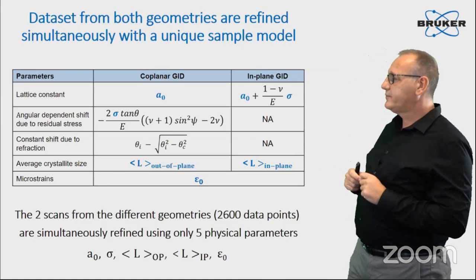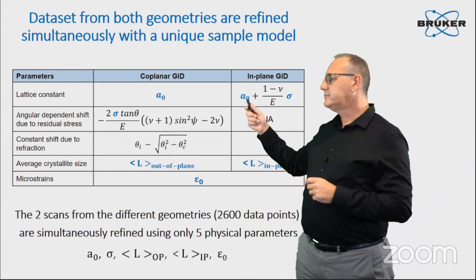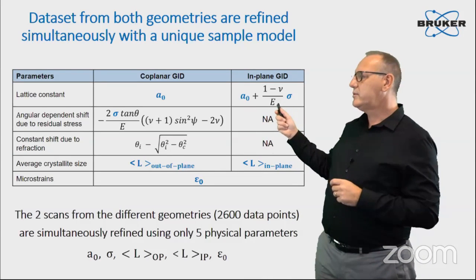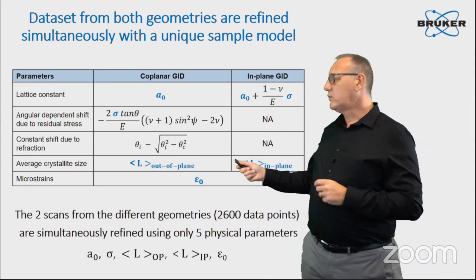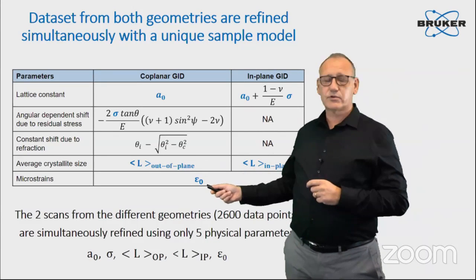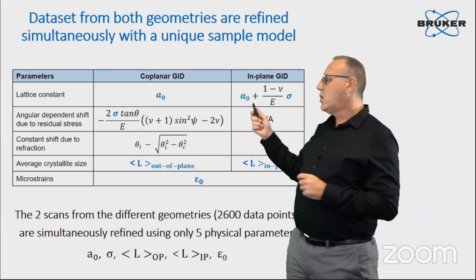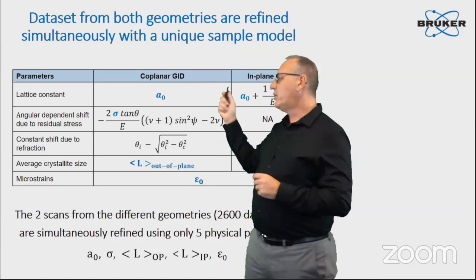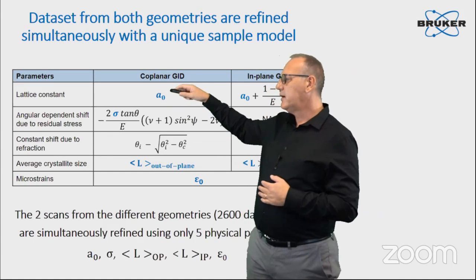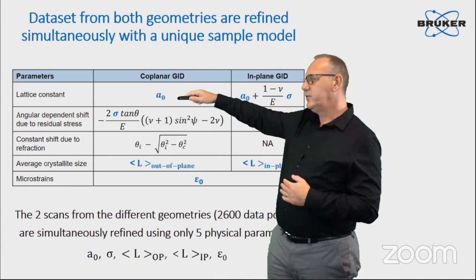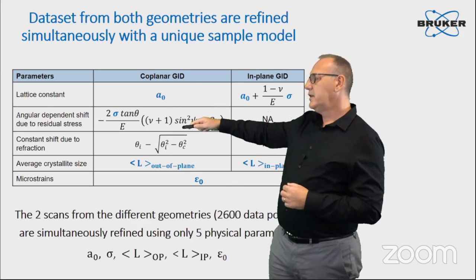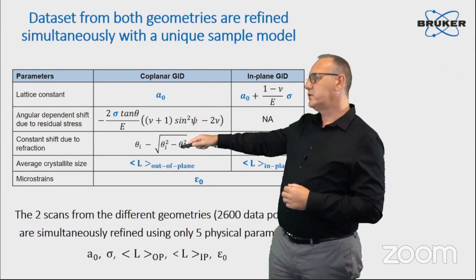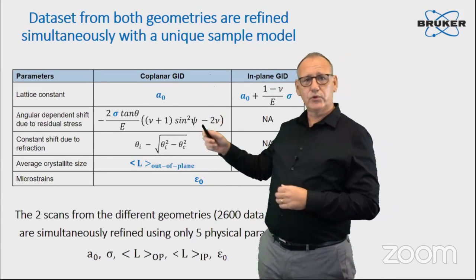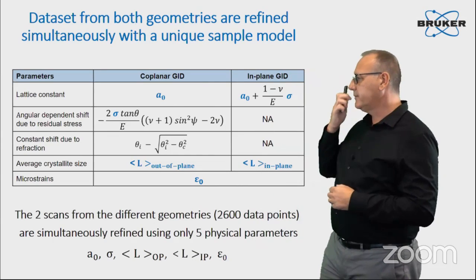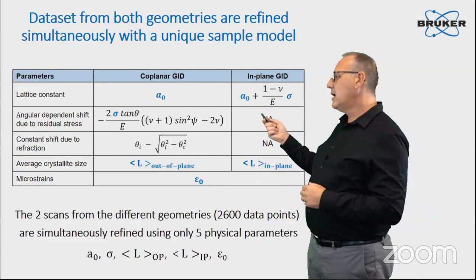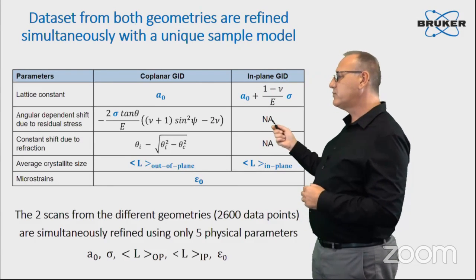What are those parameters? Those parameters are the stress-free lattice parameter, a0, the residual stress in the material, in and out of plane crystallite size, and the microstrain within the crystallites. And you see those parameters intervene in both geometries in different ways. The peak position in coplanar is a combined effect of the stress-free lattice spacing of the material, the effect of residual stress, and the effect of refraction. Those three contributions together contribute to the overall peak position in coplanar diffraction. In non-coplanar diffraction, we will refine the stress in plane, and that will give us directly the peak position.